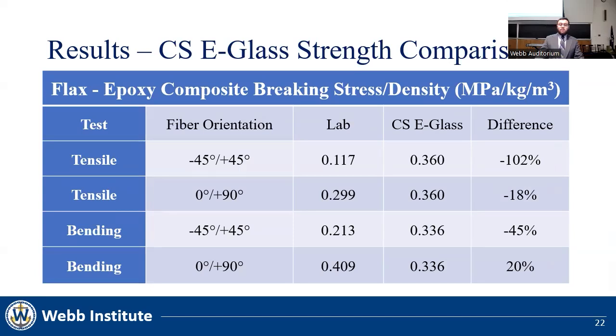Here we can see a strength comparison between the chopped strand E-glass and the physical flax epoxy composite. The flax epoxy composite is weaker in the 45-degree fiber orientation, as the chopped strand has a uniform strength in both directions due to its random fiber orientation. However, the bending is the more critical strength loading for yachts, and the flax epoxy composite exceeds the strength of E-glass when the 0-degree fiber orientation is utilized.